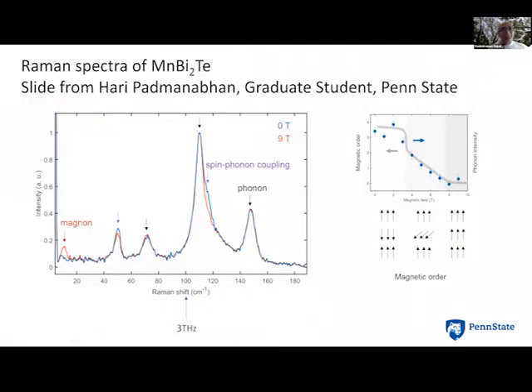Because we are currently doing Raman spectroscopy, I got a slide from Hari Padmanabhan, a graduate student here at Penn State. In my group, we are studying MnBi2Te4, the 4 went missing there. But here is the Raman spectrum from this compound. It's a topological insulator. Crystals were grown by Ziqiang Mao. You see a bunch of peaks. All of these peaks represent different vibration modes in this crystal. The atoms are vibrating. They are different vibrational modes. You can assign them to different symmetries and irreducible representations. So these are all individual, coordinated dances of atoms in this crystal.